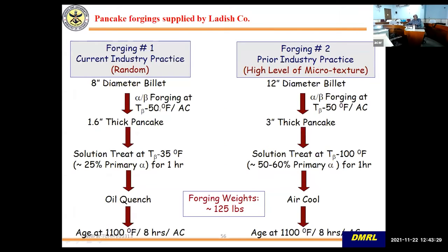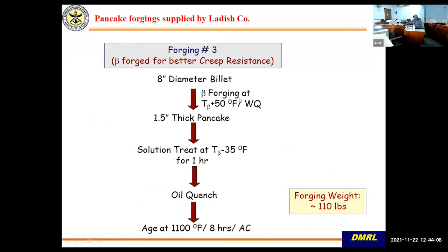Now how were these processed? One was processed by alpha beta forging at T beta minus 50, that is for random microtexture, and then heat treated at T beta minus 35, oil quenched, and then aged. And the one for higher microtexture was forged at T beta minus 50, but solution treated at a much lower temperature to have higher volume fraction, that is T beta minus 100, and then air cooled and aged. Then the beta forged material is processed in the beta condition, and then solution treated at T beta minus 35, oil quenched, and then again aged.